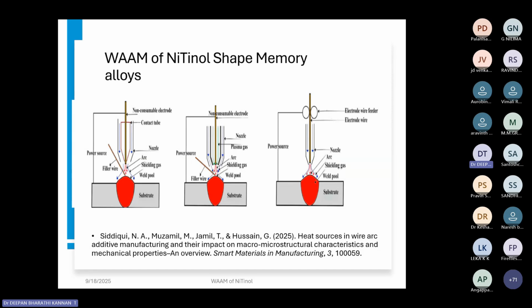If you take this MIG welding power source, it may have a good deposition rate, like around 2 to 3 kilogram per hour. Whereas laser based powder bed fusion has only around 150 to 200 grams per hour. You could see how big the difference is. In wire arc additive manufacturing, the deposition is around 2 to 3 kilogram per hour, whereas in the case of powder bed fusion, it is only around 150 to 200 grams per hour. And with respect to electron beam, it is around 600 to 800 grams. Still, it is lesser than wire arc additive manufacturing.